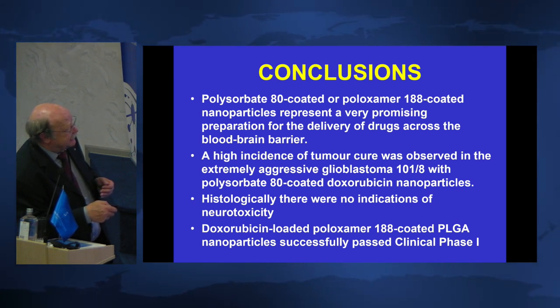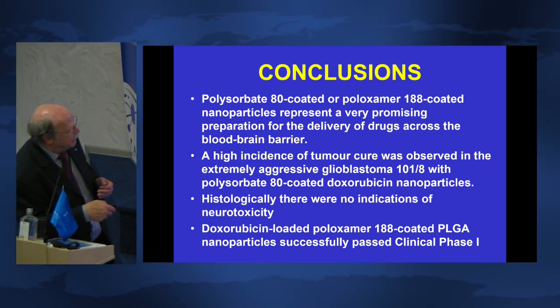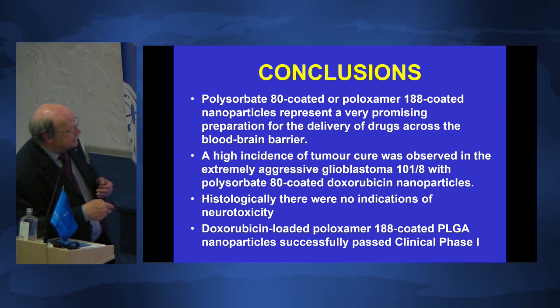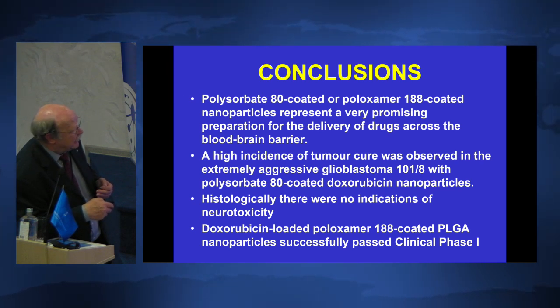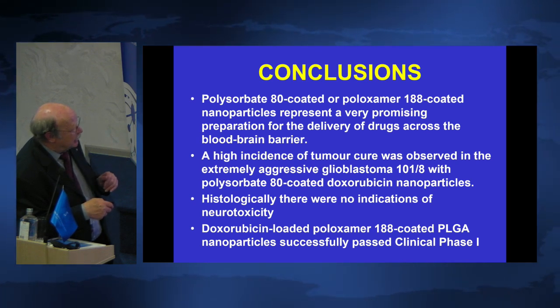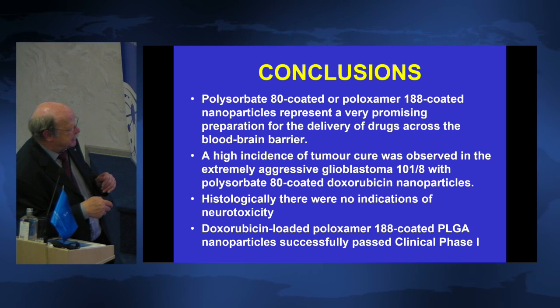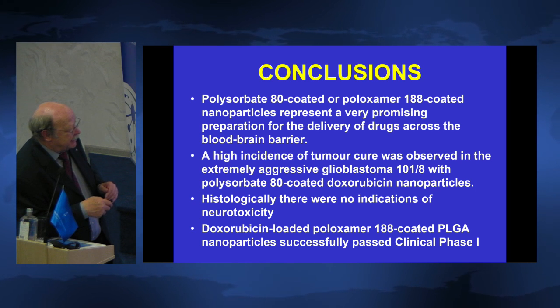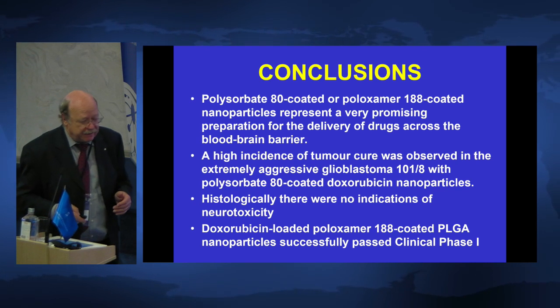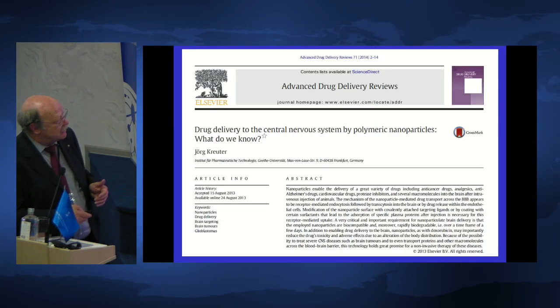Polysorbate 80-coated or poloxamer 188-coated nanoparticles represent a very promising preparation for the delivery of drugs across the blood-brain barrier. A high incidence of tumor cure was observed with the extremely aggressive glioblastoma 101/8 with polysorbate 80-coated nanoparticles. There was histologically no indication of neurotoxicity, and the doxorubicin-loaded poloxamer 188-coated PLGA nanoparticles successfully passed clinical phase 1 and, to my knowledge, are now in clinical phase 2.